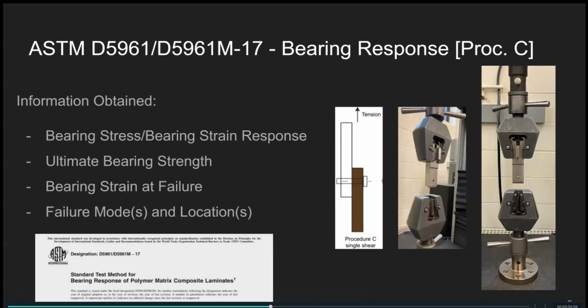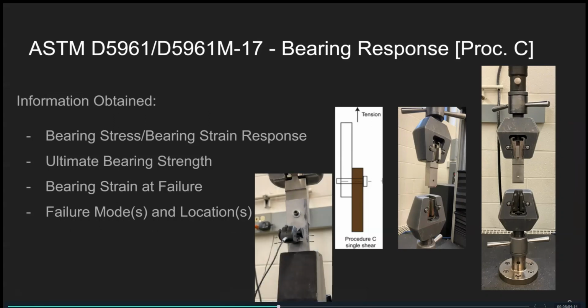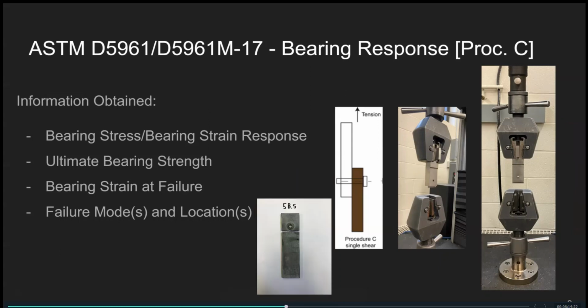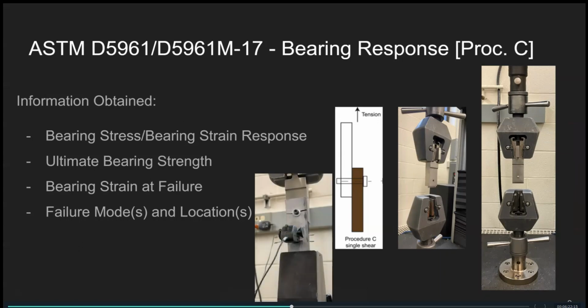And in the same vein, ASTM 5961 covered the bearing response. So it simulated the pull-out strength of a fastener if the antenna or end-use product were fastened using a bolt of some sort. The information obtained from this was the bearing stress and bearing strain response, ultimate bearing strength, bearing strain at failure, and the failure modes and locations. Turns out that the material is very brittle, as Drew mentioned, so we didn't really see much yielding. Rather, it was an abrupt break for many of the pieces.